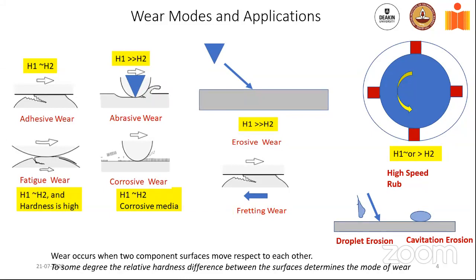Now you take the same sharp angular particle and throw it into a water slurry or throw it into an airstream and let it go and impact. You have solid particle erosion, which is what is shown. Fatigue wear, I'll skip it for now. Corrosive wear. Fretting wear becomes a very important one because that's something that actually bites us quite a bit in the industry all across. So you have two contacting surfaces undergoing motion in two opposite directions. So they're kind of going back and forth against each other, and that leads to a form of damage which is quite severe. You can either have fretting fatigue or fretting wear, but I won't get into those nuances.